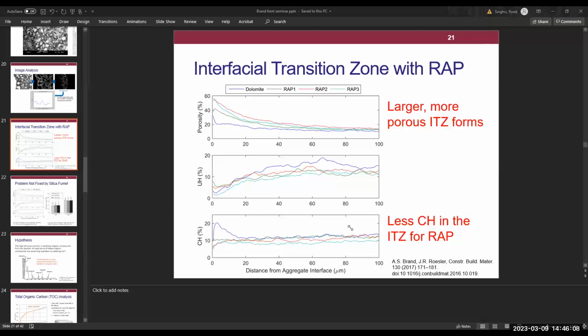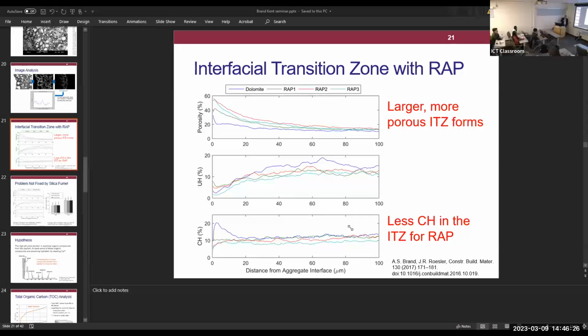Supposedly your leachates were reducing the organic content, but you're not really getting a lot of the total organic out of the RAP, the asphalt. I'm not sure you're getting a whole lot out by leaching. Correct. That's why we suspect it's only affecting the ITZ. Once we mix the RAP leachate into concrete, it only extends 100 microns away from that interface, which is why we're forming that larger, more porous ITZ but don't appear to be affecting the bulk microstructure.